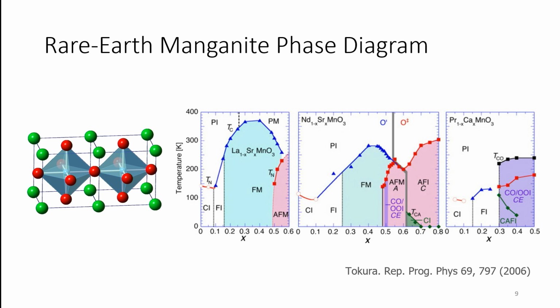You can also replace lanthanum with neodymium. Both of these ions have the same 3+ charge, but the effect of doing that is that you are changing the effective ionic radius occupying this site in the structure. So what happens then, I'm going to show you, is that in addition to changing the radius as you go along this series, you're also effectively changing the structure. And that can lead to changes in what the phase diagram is going to look like.